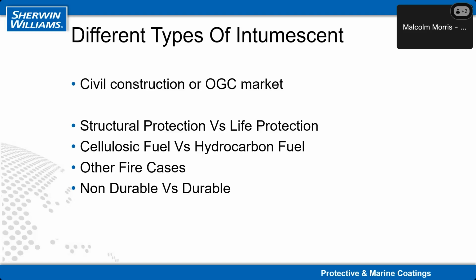But the durability of intumescent coatings is also a big question mark because intumescent coatings are designed to give fire protection, and inherently the raw materials used in there are quite water sensitive, so intumescent coatings can be susceptible to weather damage if they're not adequately protected. So you have to be careful which intumescent you specify in which environment, and also careful selection of protective sealer coats to protect the intumescent from damage from water ingress.